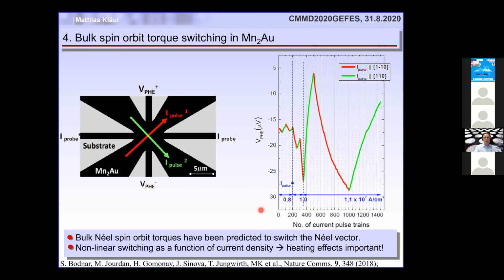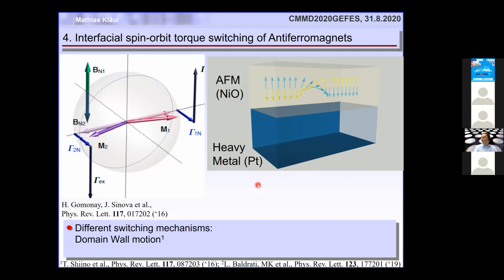So something which would be even nicer is if you were able to switch also an antiferromagnet that has not this asymmetry breaking, because there are not many systems where this exists. So here we have a simple antiferromagnet, nickel oxide, with no asymmetry breaking, and we put platinum on top.